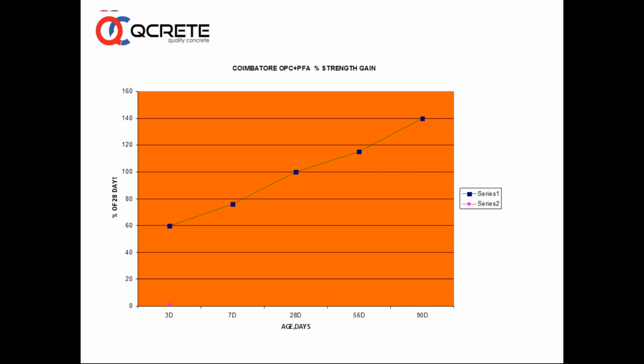Here it shows that the jump between 28 days and 90 days is about 40%. We have found this jump around 20% in some places, 23% to 30% in Bangalore, and in other places as good as more than 35%. For example, here in Coimbatore, when we used Tuticorin and Mettur fly ash, it has gone up to 40%. So in short, there is a significant growth of strength beyond 28 days when we are using supplementary cementitious material, which is an offshoot of our quest for durability.